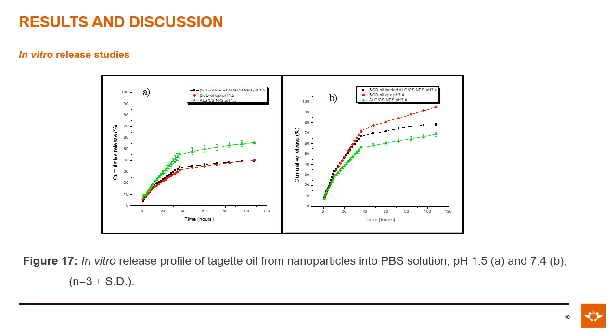The release patterns from the different nanoparticle formulations were biphasic, comprising an initial quick release followed by a sustained continuous phase. The beta-cyclodextrin oil inclusion complex released tagette oil at a higher rate than the beta-cyclodextrin inclusion complex oil and alginate chitosan nanoparticles. In the case of the cyclodextrin-containing system, only 26% of the oil was released after 24 hours, while 33% was released in alginate chitosan nanoparticles without cyclodextrin. This suggests that beta-cyclodextrin nanoparticles can be more effective in protecting the loaded drug in the gastric fluid, allowing a greater percentage of the drug to reach the small intestine, which is the main absorption site into the blood system.